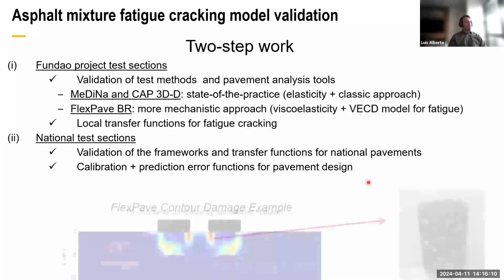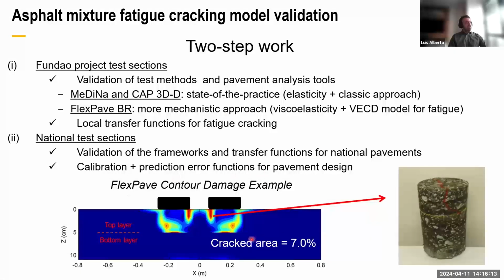This is a very important point here. It looks simple, but it was very important for us because in order to validate the system at the beginning, we need to see if the analysis results were reasonable. So in this case, we have a bottom asphalt layer and a top asphalt layer. The bottom layer has a very nice fatigue performance, and the top one is in terms of fatigue really poor. So when you run the analysis, the system showed us the upper layer totally damaged. So the question is, what is happening?